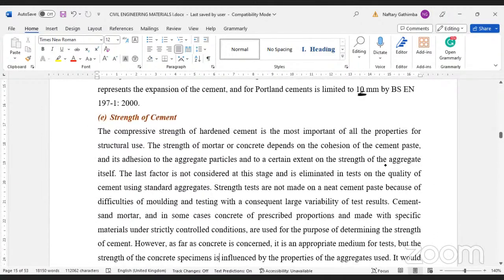Now, the strength of cement is the most important, because even if the cement has all the other good properties, good fineness, good soundness, good setting time and all that, if the strength is not what we state, then it has not met our requirement. Something you should notice is that I have given you the strength of concrete, but I have not given you the strength of cement. So we have cement like the Portland pozzolanic cement, referred to as class 32.5. Then ordinary Portland cement, we have class 42.5. Of course, we have 52.5 and 62.5, but these are the most common cement classes. So don't confuse the class of cement and the class of concrete.